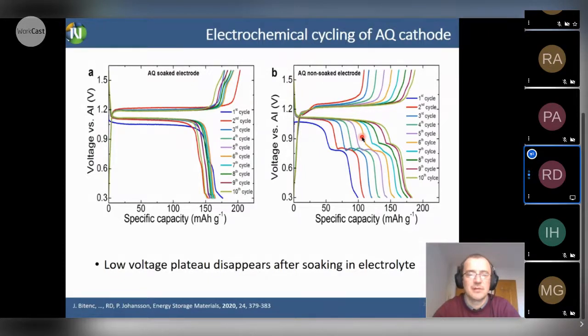very simple experiment. We simply soaked the electrode in the electrolyte for 24 hours, and then we assembled batteries with the non-soaked electrode and with the soaked electrode. And what we observed is that with the soaked electrode, this lower plateau disappears, and we have only this higher plateau. So that means that aluminum chloride in the electrolyte has an electron-withdrawing functionality on the quinone, and that increases the voltage. It's very similar to what I showed in the case of magnesium when we added aluminum chloride into the magnesium electrolyte.